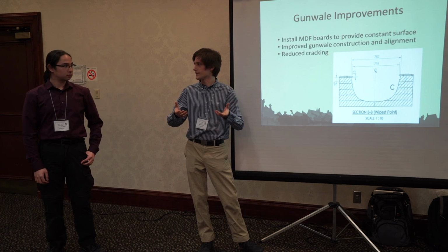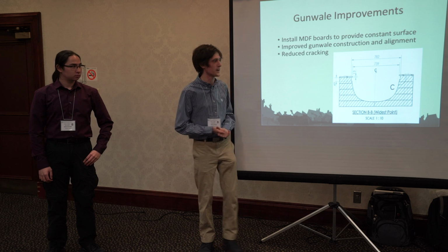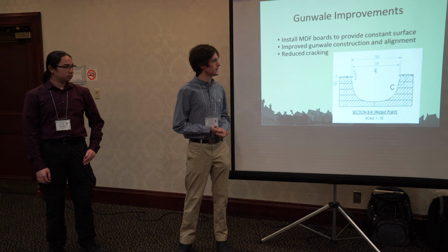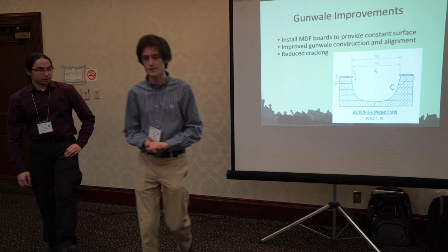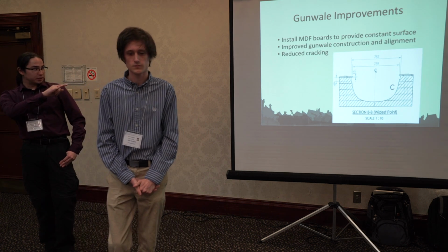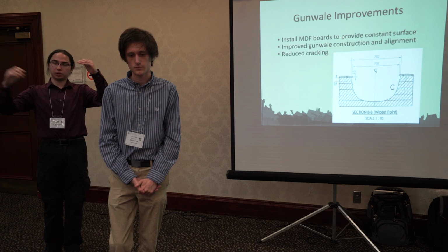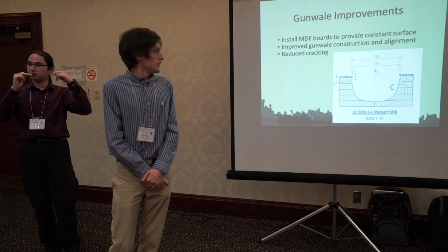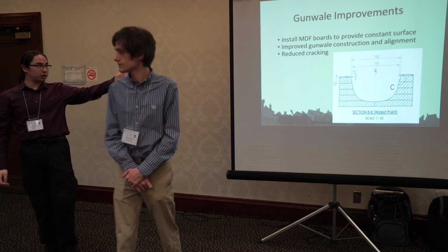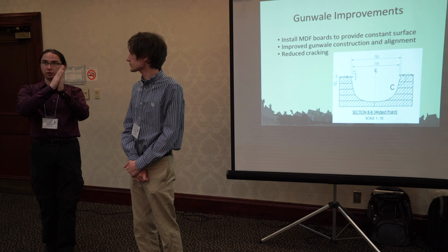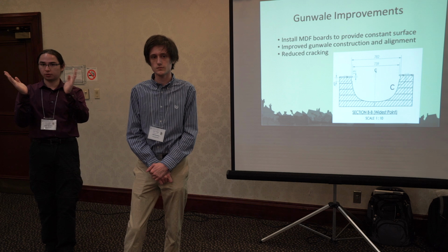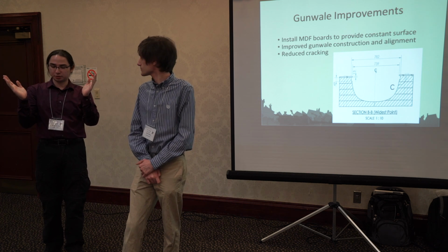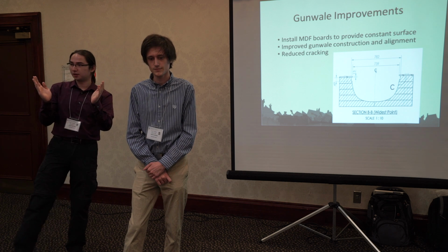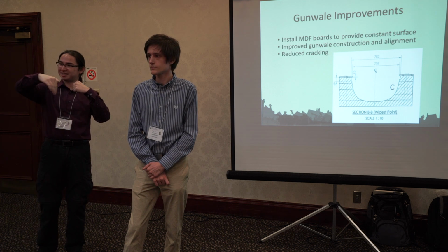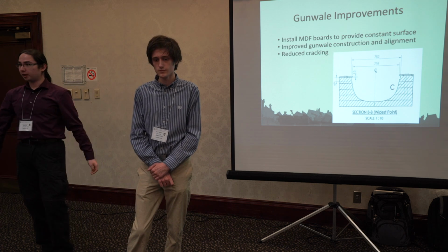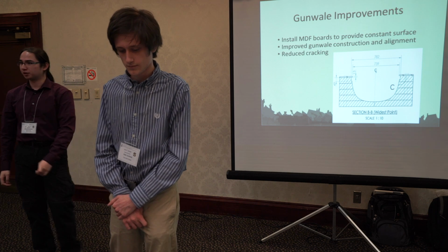One of the problems when it dries is that the gunnels crack, and providing the main structural support, it is a very bad thing if these start to go. So we reduce the cracking during the drying process. An interesting problem that came up with the MDF installation is that due to the MDF covering the top of the mold, we weren't able to check if the gunnel was properly laminated between the concrete matrices. When we pulled off the MDF boards, we found out that our inner layer of structural mix had delaminated from our internal carbon fiber mesh. Essentially what we had to do is create a makeshift mortar out of concrete mix and stick them back together with this mortar pasted in between. But we got essentially all our strength back just by doing this, and it was an interesting problem to have to try to solve.